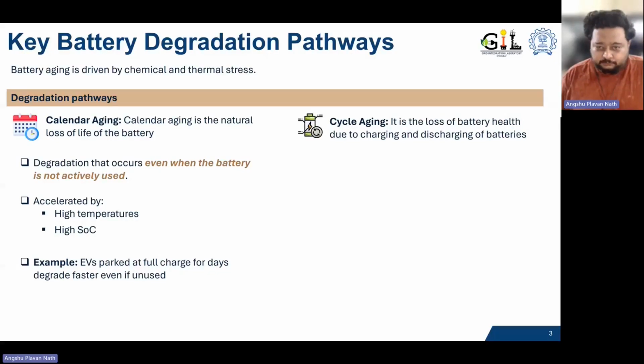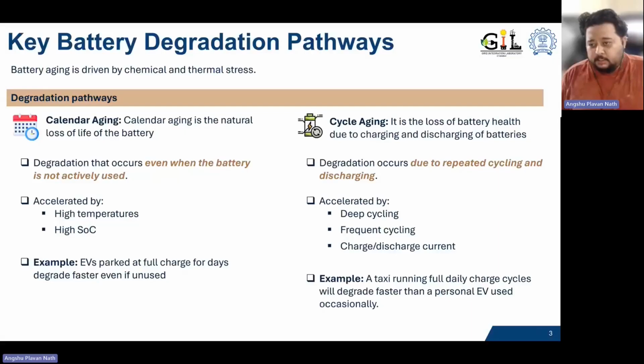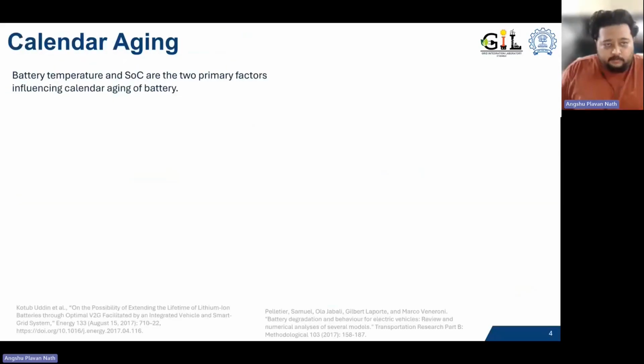of charge. So for cycle aging, the degradation occurs through repeated charging and discharging. It's dependent on the depth of your charge-discharge cycle, how frequently you're charging the battery, and the current at which you're charging or discharging the battery. For example, a taxi running full daily charge cycles will degrade faster than a personal EV used occasionally. That's a rough example.